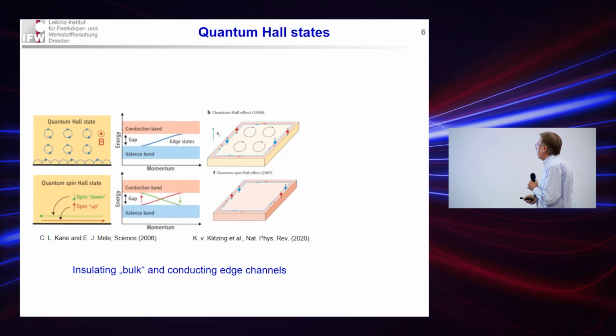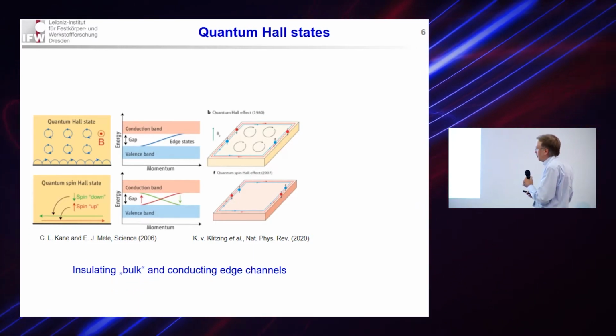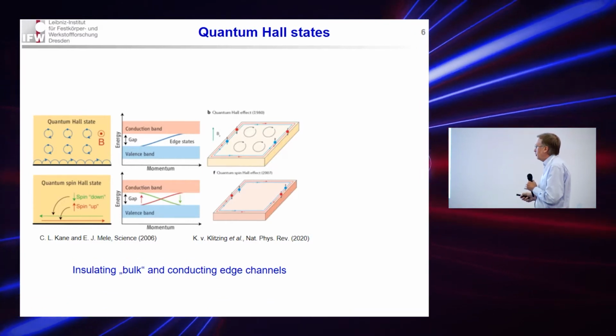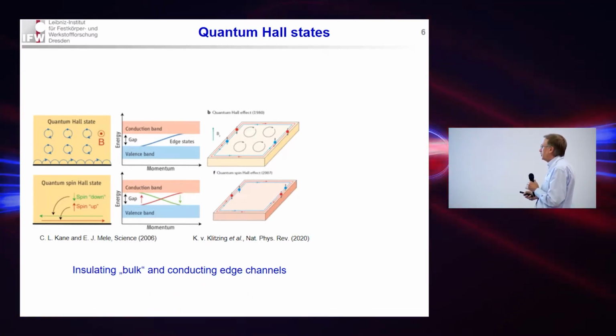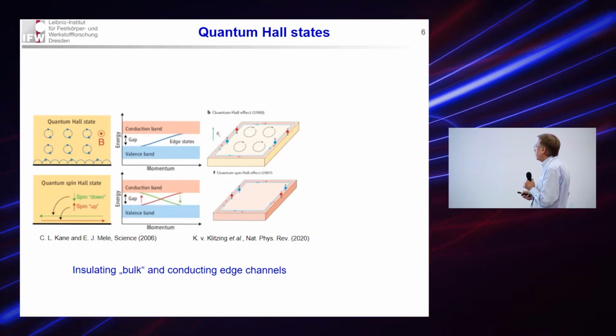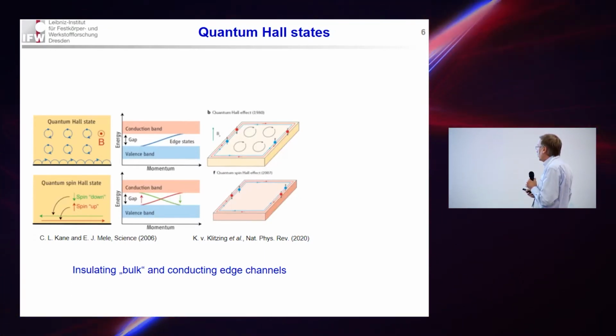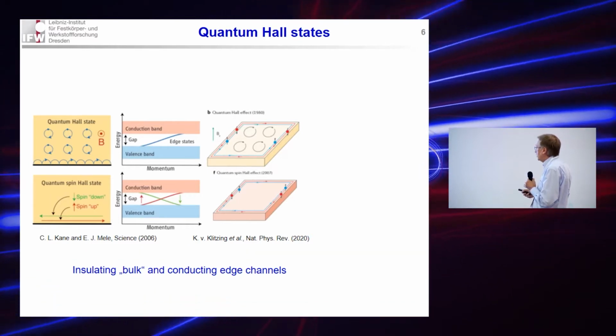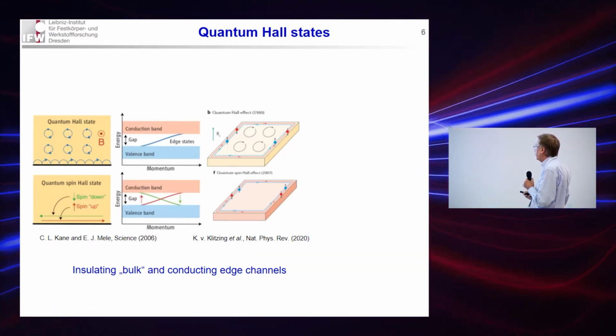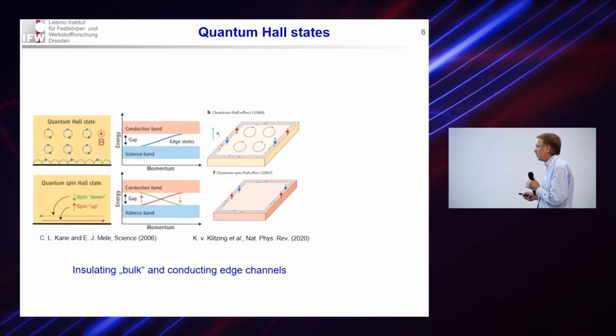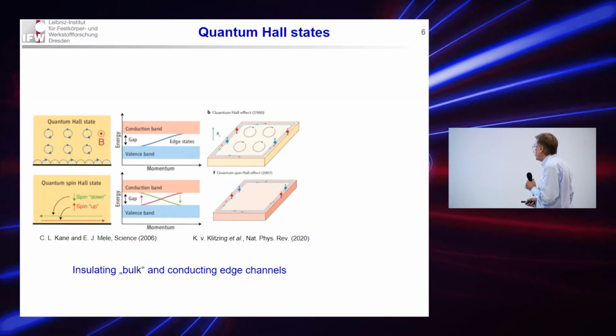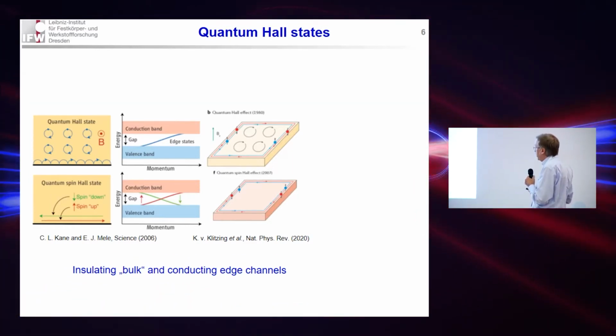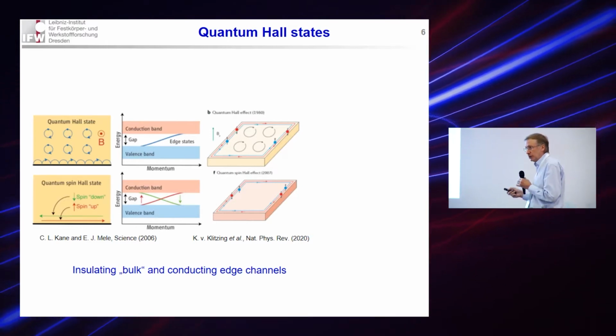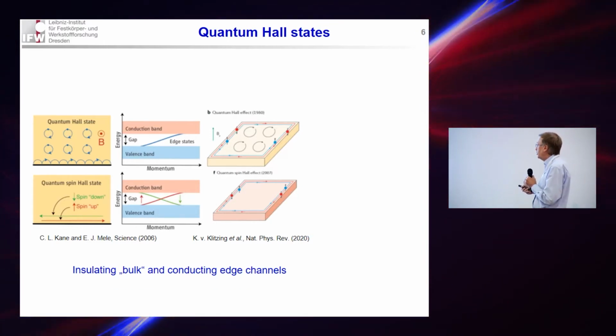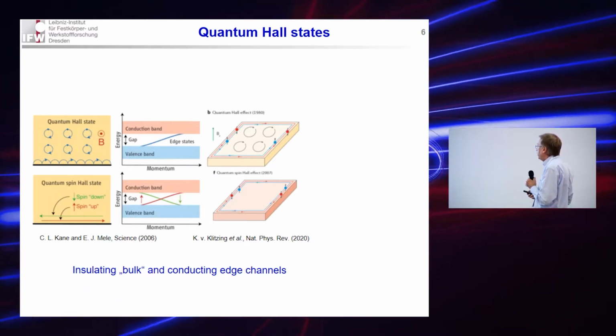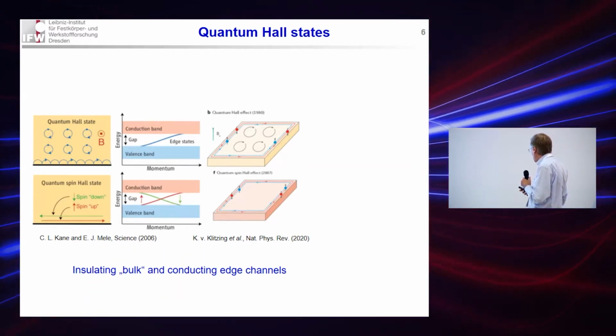That means the bulk, or so to say the surface, is insulating in a strong magnetic field, but the edges are conducting. A similar situation is expected in the topological insulator, but for that one doesn't even need a strong magnetic field. One has in this topological insulator the quantum spin Hall state, where the currents, which are now spin polarized, also run on the edges. Then one expects that if one applies a small magnetic field, one can make this surface insulating, but there will still be conducting channels at the edges.